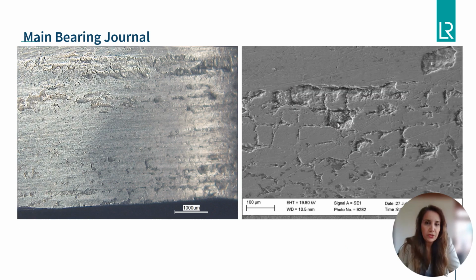Further investigation of the surface of the main bearing journal in the area of the failure exhibited evidence of spalling and abrasion marks. We further investigated these areas in order to characterize constituent features and defects along with the underlying metal microstructure. Metallographic examination was undertaken.